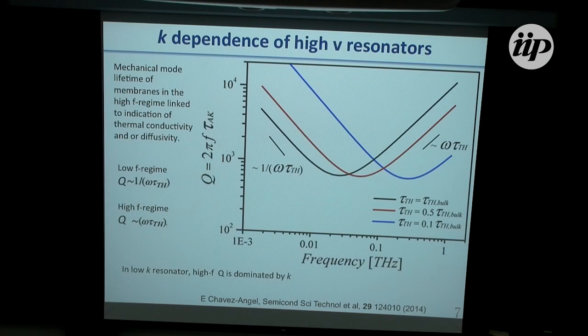The second example, and we actually had a little shot to see if we could relate the Q factor to the thermal conductivity. Basically, depending on the resonator frequency, one sees that there is a dependence of 1 over the frequency and the lifetime of the thermal phonons, which actually has a minimum.